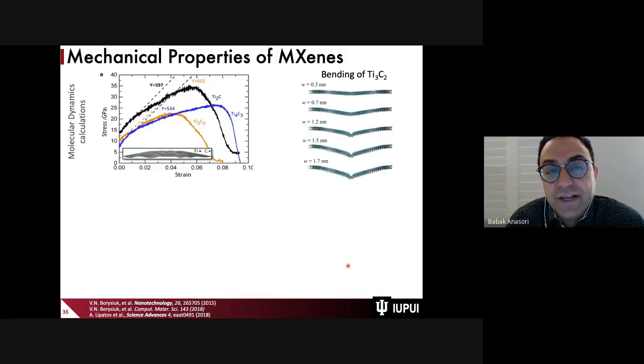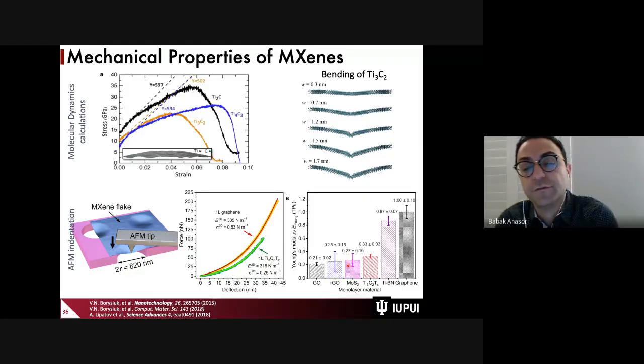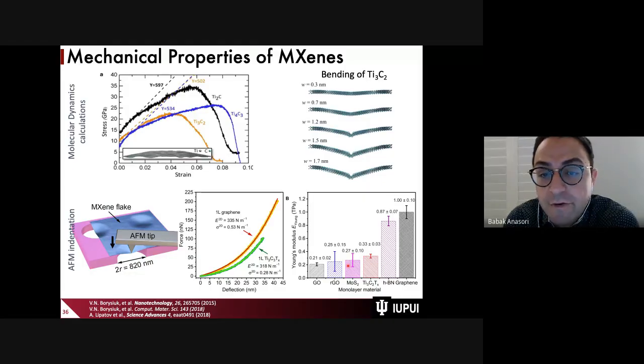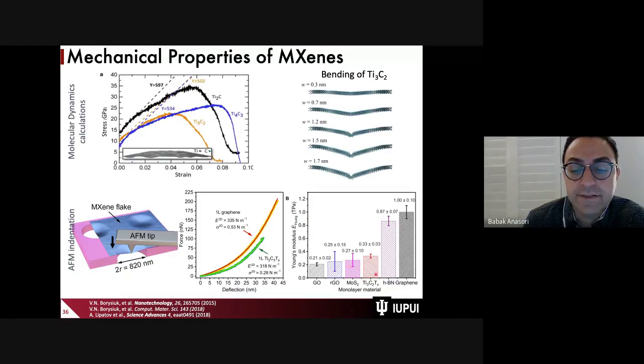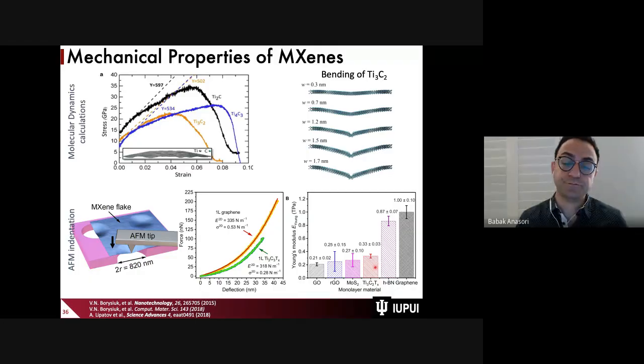As a transition metal carbide, MXenes have very high stiffness. The stiffness can be in the range of 300 to 400 gigapascal, which, if you look at all the known materials, the highest Young's modulus of all materials is for graphene, where we have 1000 gigapascal or 1 terapascal of Young's modulus. After that, we have hexagonal boron nitride. And right after that, we have MXenes. Now, these are all measured on a single atomic layer, a few atoms thick, of MXenes.